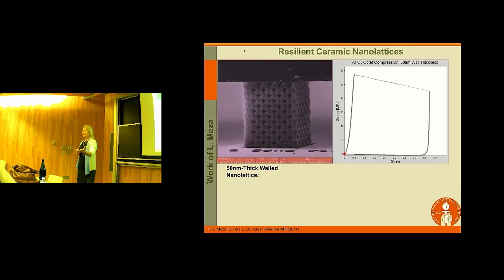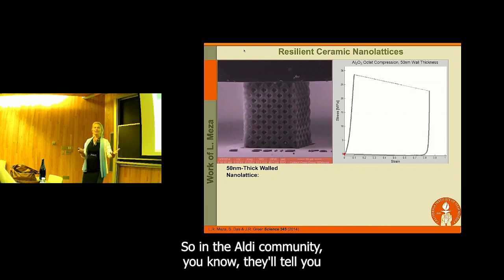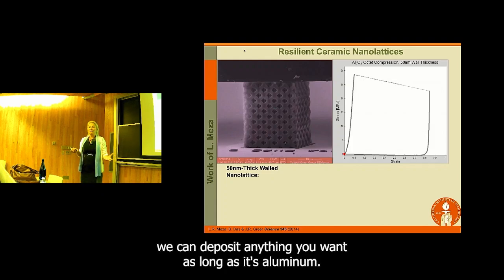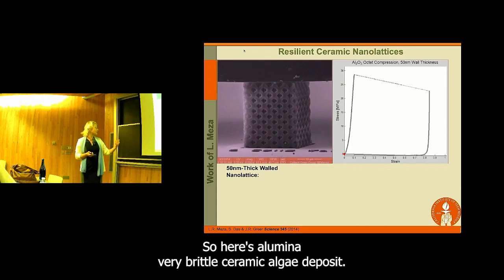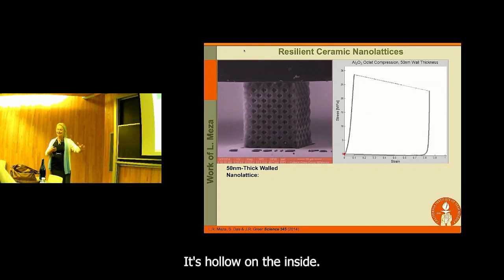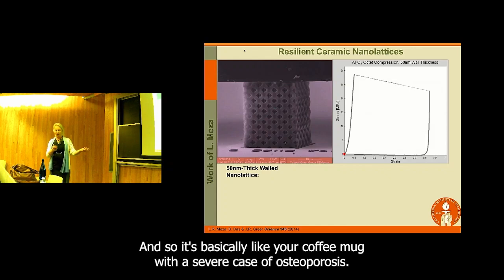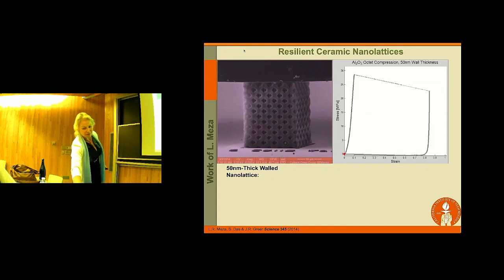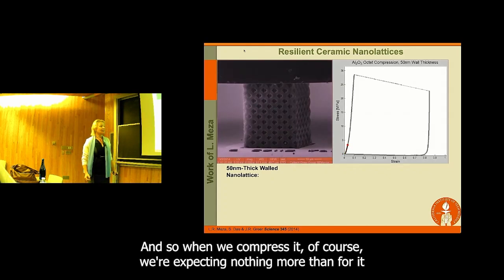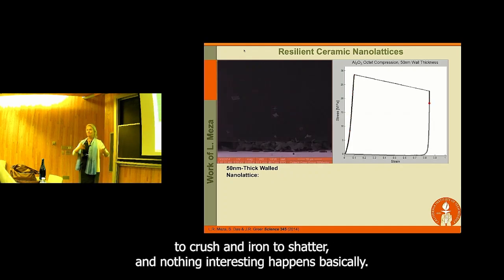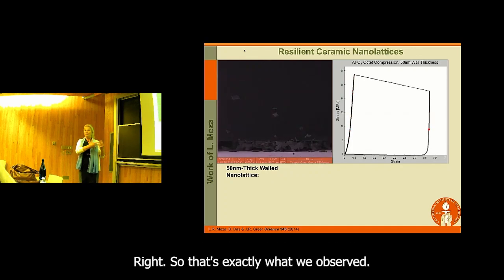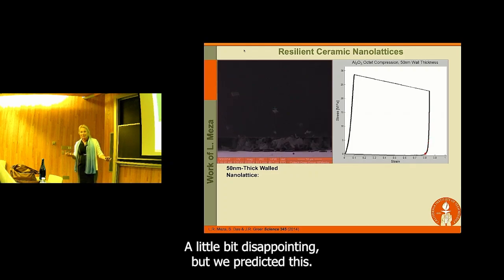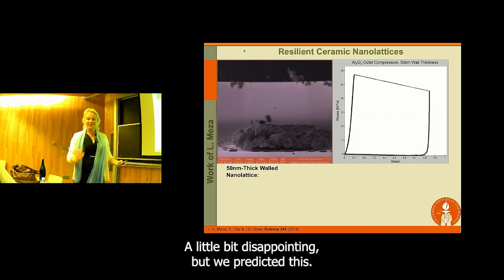ALD. Okay, all right. So in the ALD community, they'll tell you, we can deposit anything you want as long as it's alumina. So here's alumina, a very brittle ceramic, ALD deposit. It's hollow on the inside. And so it's basically like your coffee mug with a severe case of osteoporosis. And so when we compress it, of course, we're expecting nothing more than for it to crush and shatter, and nothing interesting happens, basically, right? So that's exactly what we observed. A little bit disappointing, but we predicted this, right?